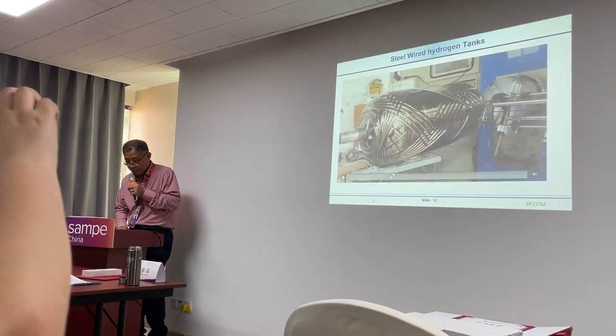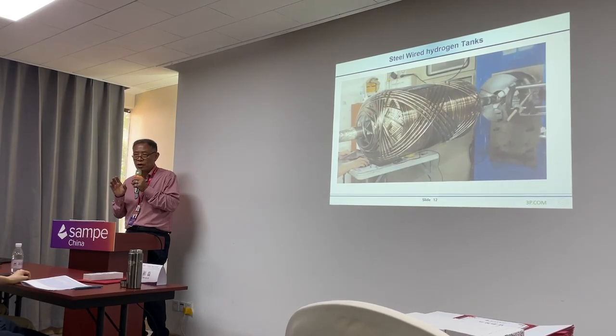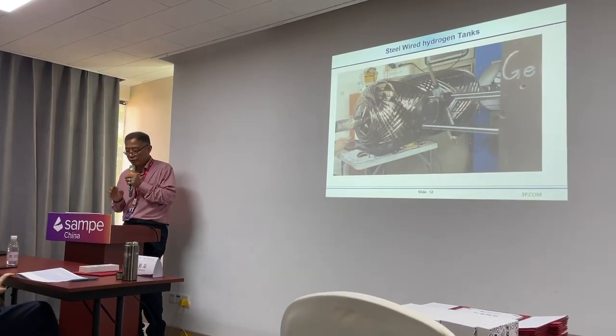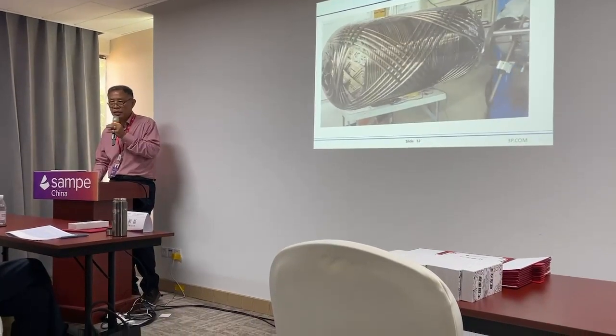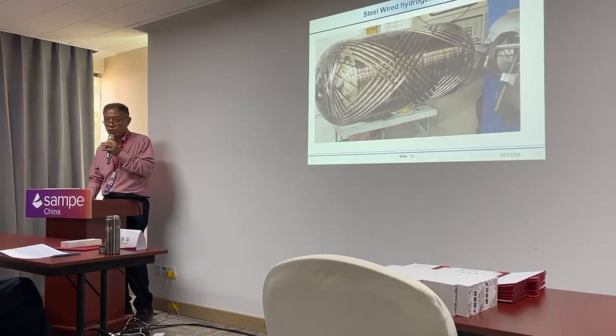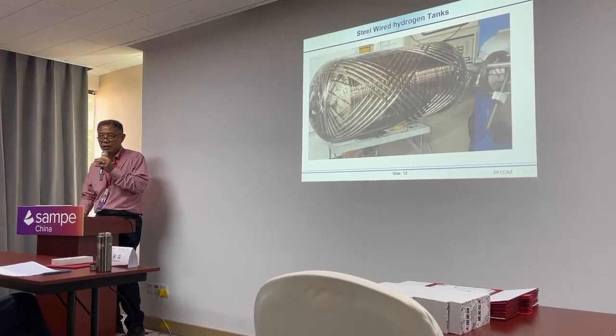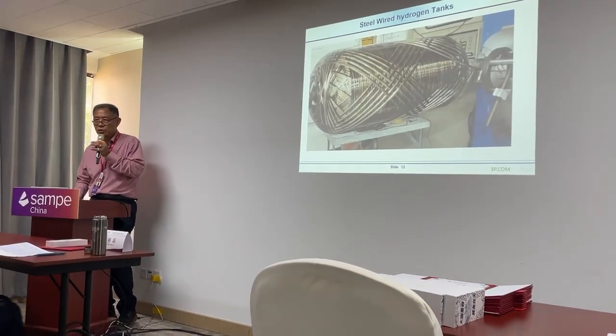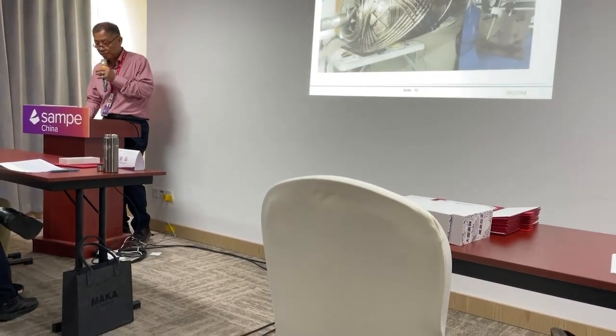And so as you can see, this is the steel wire. Not 100% steel wire. It is a combination of carbon fiber and steel wire, mostly a 50-50 ratio. The main purpose of this is that it is fully recyclable, not just the resin, but also the fibers. And we also like to reduce the cost. So total cost will be 20 or 30% less than a full carbon fiber. Well, this is a little bit heavier than carbon fibers, so this is usually for forklift or stationary purposes.